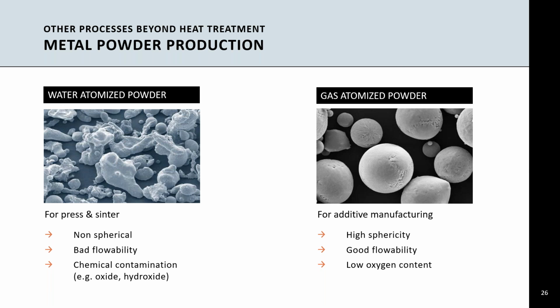Powders for additive manufacturing are usually produced using the gas atomization process, whereby molten metal stream is atomized thanks to high pressure neutral gas jets into small metal droplets, thus forming metal powder particles that you see in the right image there after rapid solidification. Gas atomization is a physical method as opposed to a chemical or a mechanical means to obtain those metal powders. But powders produced by gas atomization have spherical shapes, again, like you see in the image to the right, which is very beneficial for flowability, repeating what I already mentioned.